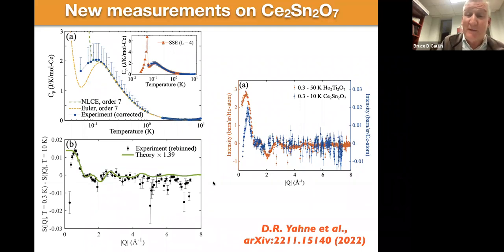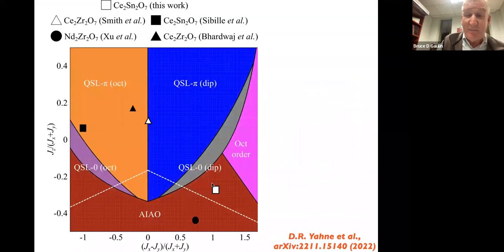But the point is that if you place cerium stannate in this part of the phase diagram, you don't expect there to be significant diffuse scattering out in that region, and in fact that's consistent with what we measure. So our data set is internally consistent, I would say.